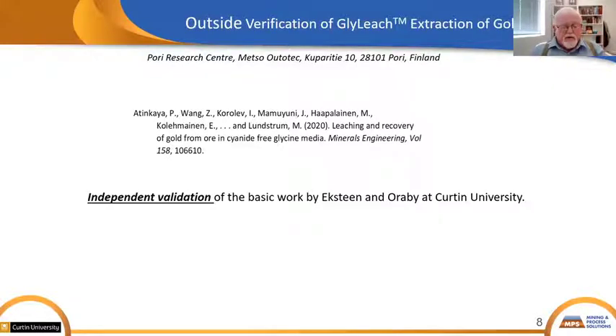It showed that addition of activated carbon to the pregnant leach solution can provide a 100% recovery of the gold that has been leached, and it surprisingly gave a superior dissolution compared to straight cyanide with an epithermal ore that did contain significant gold as tellurides.